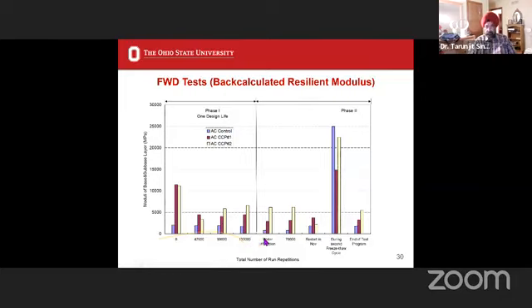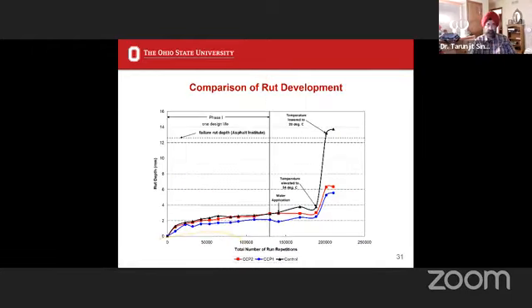And this then shows you water infiltration. This is not representative data because this was done during a freezing cycle. When something is frozen, its modulus obviously will be very, very high. This is what we found at the end of the testing: for the CCP pavements, the asphalt concrete pavements had resilient modulus 2 to 3 times that of the control sections.